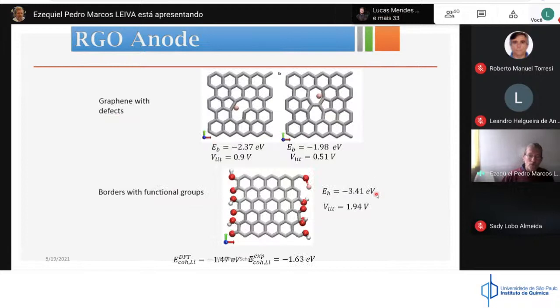Well, you can also play around with lithiation defects. This is, for instance, the binding energy of a lithium atom in this defect. And you can see that this is the insertion potential. If you have a defective graphene surface, you expect also to have an insertion potential which is higher than the insertion potential of lithium.